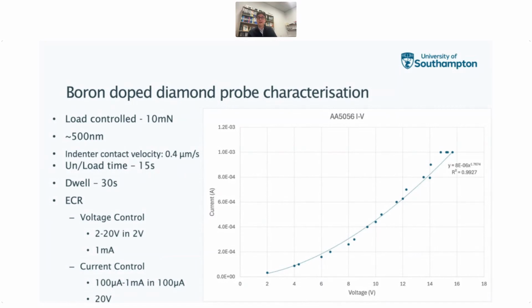And you see you get this power type fit to this curve. For boron doped diamond, this is quite characteristic, where you have this sort of curved response of the boron doped diamond in the IV curve.